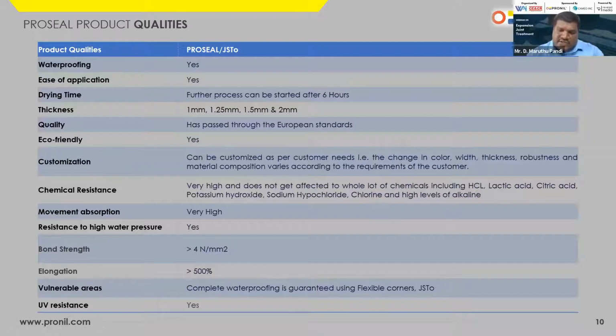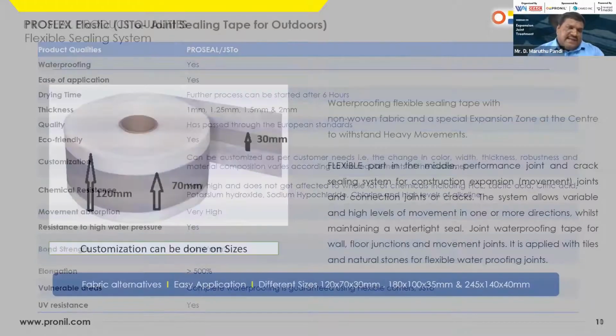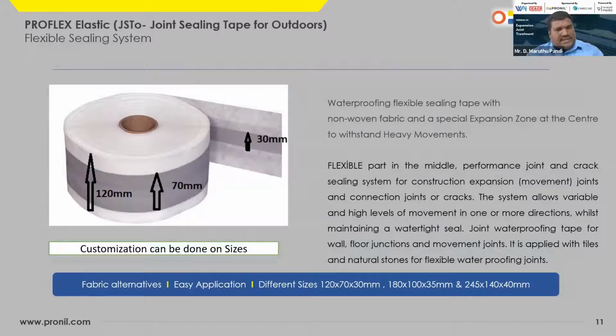ProSeal is a product, an expansion joint tape, which can come in plain as well as with a non-woven on both the sides. Something like this you can see. TPE material of 70 mm width, and a total 120 mm width of non-woven on both sides, with a flexible zone in the center of 30 mm. This is also customizable according to the required width. If the joint is 25 mm or 20 mm width, we can go with 120, 70 by 30. If it is more than 50 mm joint, we have to go for a higher size of 180, 100 by 35.